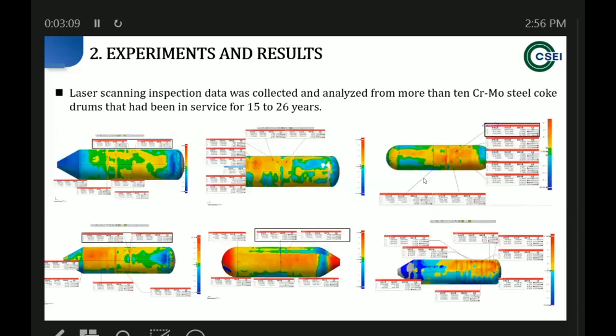We did data collection on about 14 coke drums, and we used laser scanning to obtain their profile. Here we can see some samples. We can see some deformation is at the top of the coke drum, and some of it is concentrated at the bottom of the coke drum. They are in different locations.